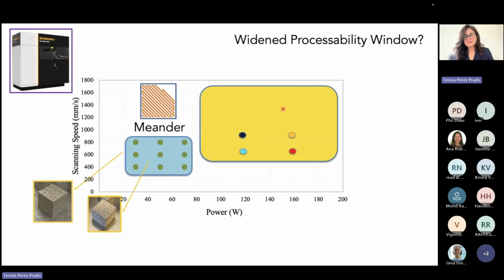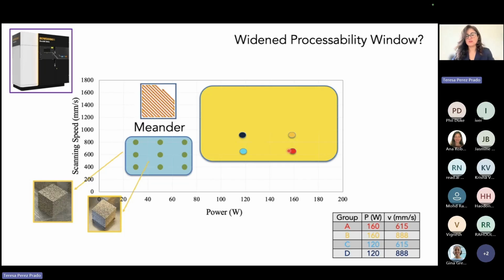And we thought, okay, let us see if we can now, using time delays, process the material in this region that was before forbidden. Because we have high power, there is a high chance that we have higher density here. So we tried 4 conditions, groups that we call A, B, C, and D. A is this here in red with the higher volumetric energy density, and dark blue here is the lowest volumetric energy density. So we fixed these 4 groups, and we added time delays, from no time delay, which is the default value, to 300 milliseconds. So let us see what happened then.